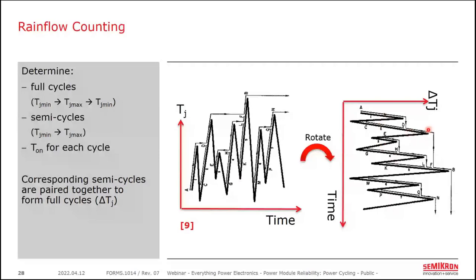And then you can visualize drops of water flowing down this roof here, where each droplet starts at, in this case, the minimum value starting on the right. So we start on the right side of this graph, and we have droplets of water flowing down. And there are a set of three or four rules that you use about where the droplet comes together with an earlier droplet, or if the droplet falls off the edge of the graph, that allows you to count partial delta Ts.